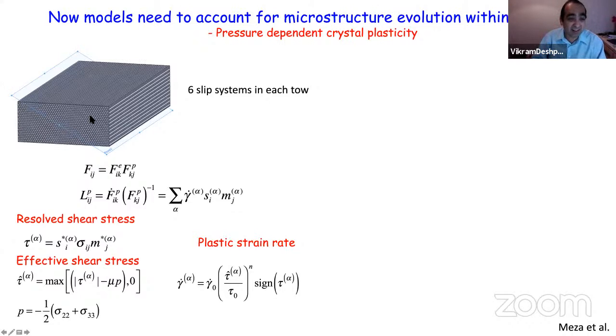But also there's something more interesting, which is that these fibers are rigid compared to the matrix. And so this is like a granular medium. And like any other granular medium, you'd expect pressure sensitivity to be there, because effectively as these tows move, they have to sort of move apart a little bit. And so there's some kind of local dilation effect happening. So this is a very straightforward crystal plasticity model with pressure dependence, of course, included in it.